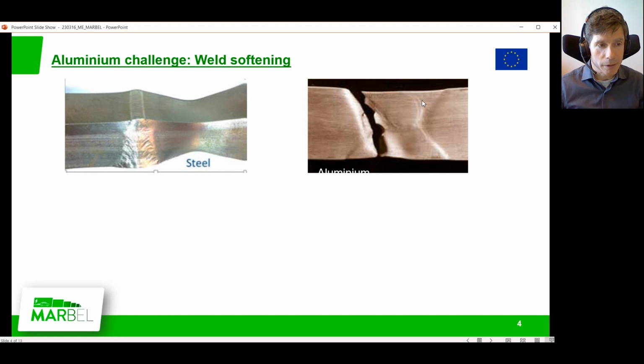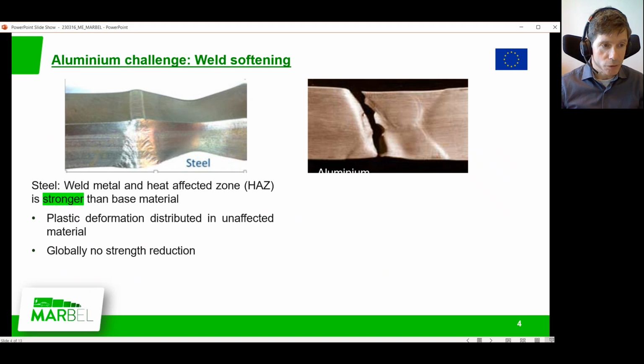If you compare an aluminium weld towards a steel weld, in the steel weld you can choose a weld material, and the area surrounding the weld, close to the weld, is often harder and stronger in yield strength than the surrounding material. So the plastic deformation, in case of a crash or in use, is distributed in the surrounding material, which doesn't create a weak link in the weld. So globally, there is no strength reduction because of the weld.